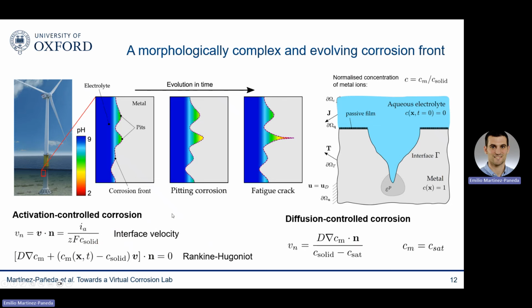And when the concentration of metal ions reaches the saturation value, then instead you have diffusion control corrosion, so that the concentration of metal ions is given by this Dirichlet boundary condition, and the interface velocity is given by sampling the saturated concentration on the Rankine-Hugoniot condition. So you have to impose on the moving corrosion front boundary conditions of various types, Robin, Dirichlet, that are varying in space and time. This is simply a computational nightmare, and the reason why computational mechanicians have not been able to deliver models to predict the evolution of the corrosion.